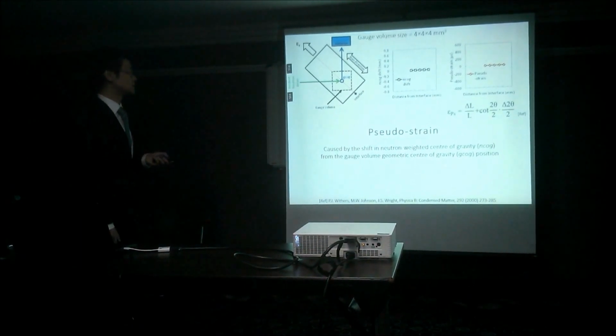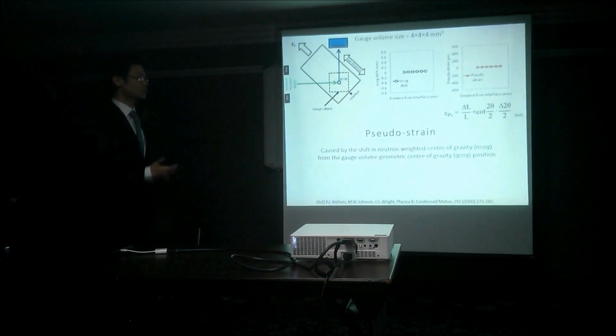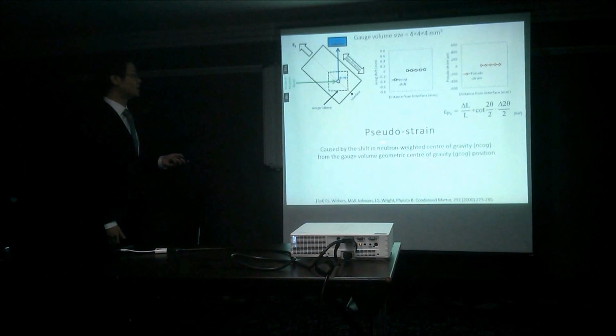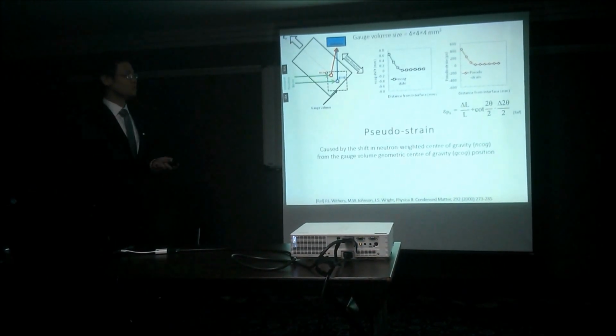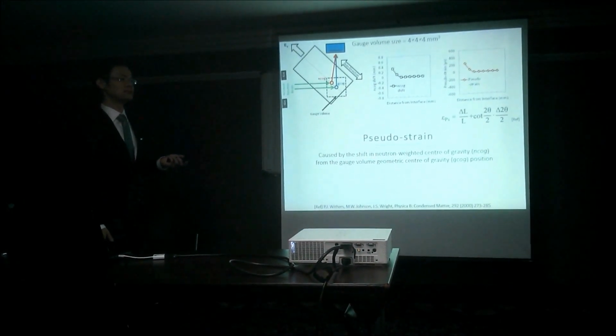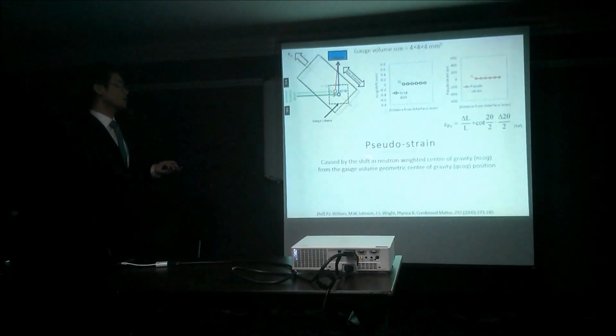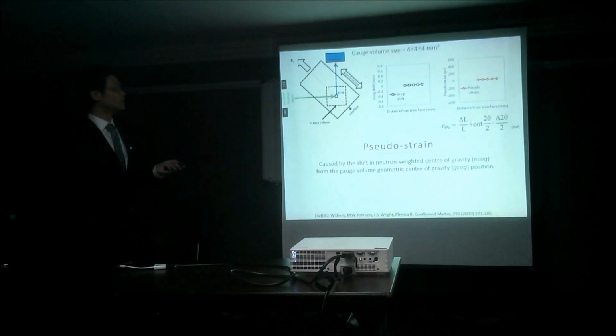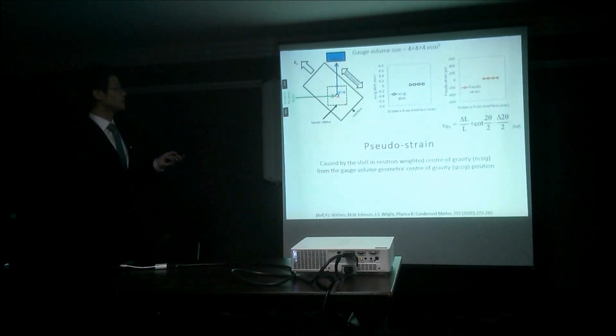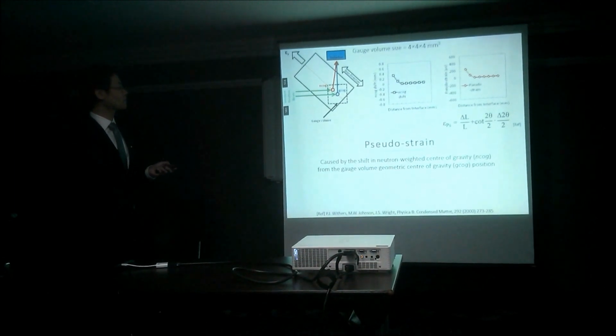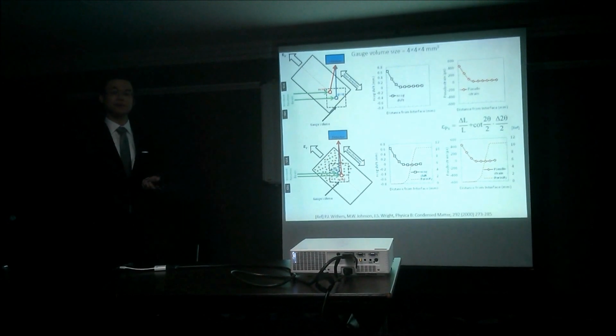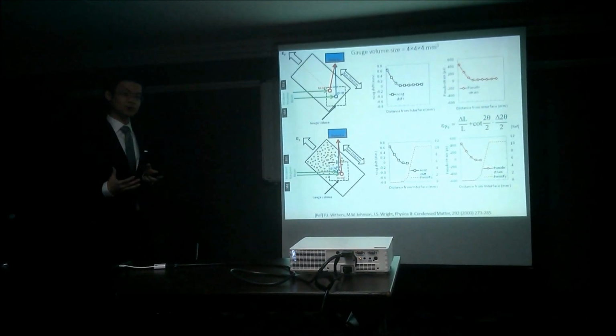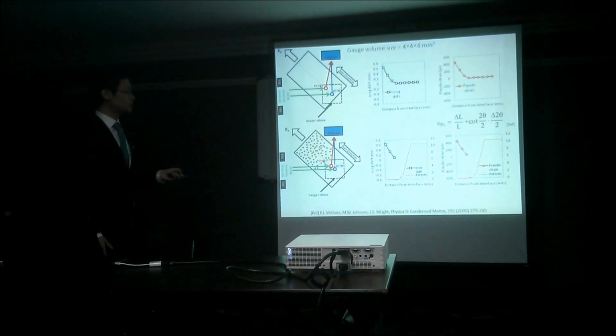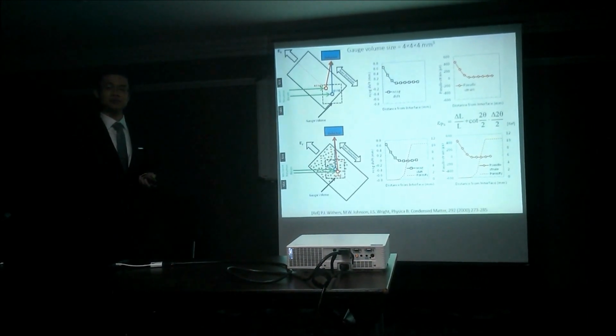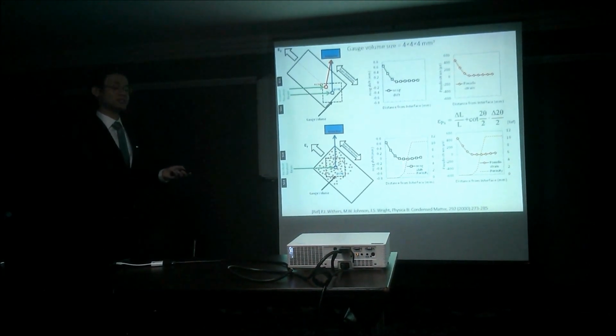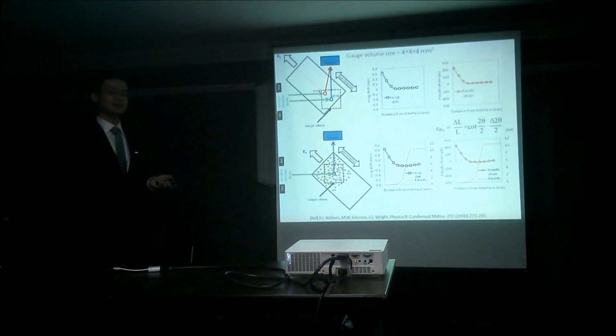What if we scan towards the surface, let's say to the interface? We then have an incompletely filled gauge volume, leading to a shift in the neutron center of gravity. We can estimate this shift by using a weighted center of mass calculation. And this shift causes pseudo-strain, which is dependent on the neutron flight path change, delta L, and the angle change, delta theta. Right. So what if we have a porous layer in our sample? As the gauge volume enters the porous layer, the neutron center is shifted to the denser part, leading to pseudo-strain. Compared to scanning out of the sample, pseudo-strain caused by porosity is much smaller.